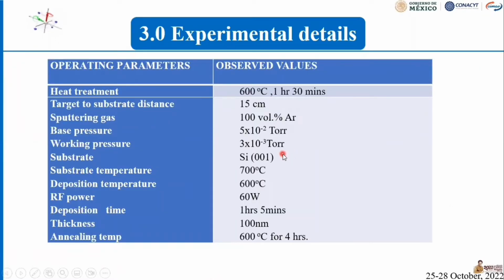Here are the experimental details. Before deposition, a 1 by 1 centimeter square section of the substrate was sonicated in acetone for 10 minutes, then cleaned by successive rinses in an ultrasonic bath of distilled water for 10 minutes, then with alcohol for 10 minutes, and deionized water after each solvent. The purpose of this cleaning was to remove organic residue from the silicon, and it was blown with dry air before loading into the chamber. Inside the chamber, these were the parameters with the corresponding observed values.